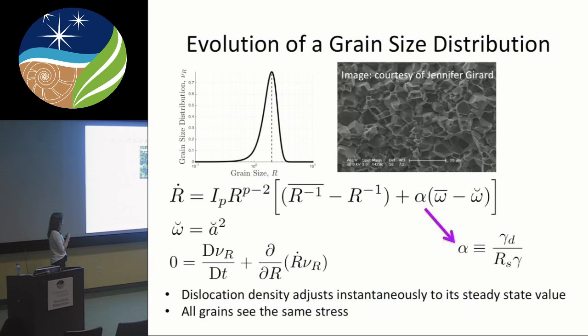So the mathematical model looks very much the same. Grain size evolution, where R now stands for any population within this grain size distribution. The math looks quite similar. You're now comparing the evolution of a given population to some mean grain size, and this mean grain size is determined by mass conservation. And similar for the dislocation density.